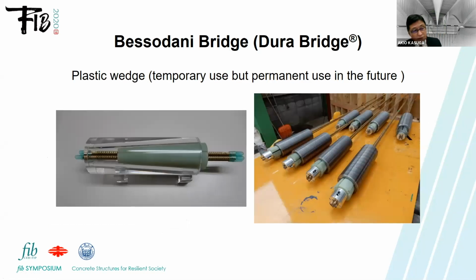And also, as I said before, the temporary prestressing for the pretension is used only once. It is one reason for the cost being higher than the conventional technique. So in this project, we developed the plastic wedge like this, a joint development with a plastic company. In this case, we use a steel pipe, and the wedge is plastic. But we can use this wedge about 10 times, and we can reduce the cost in this project.